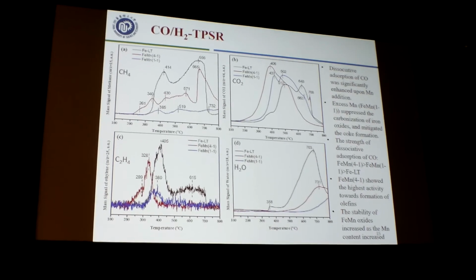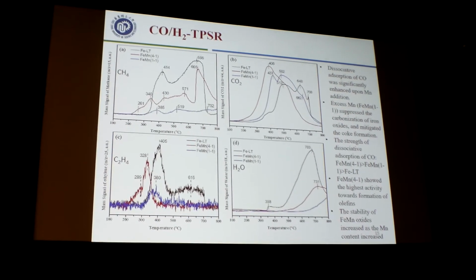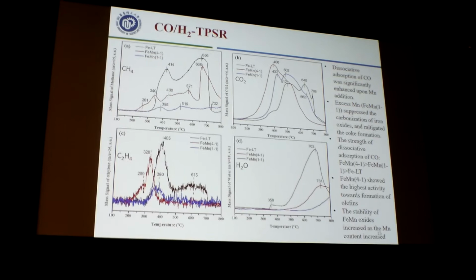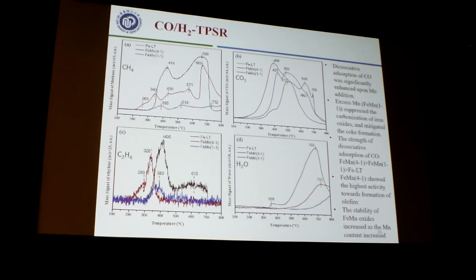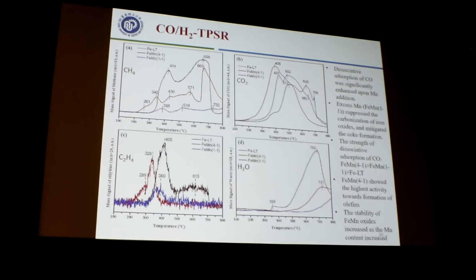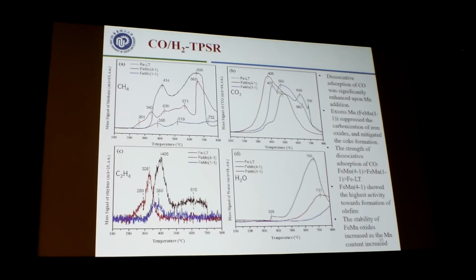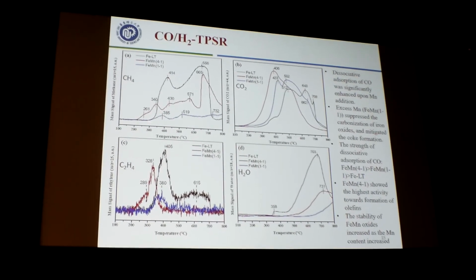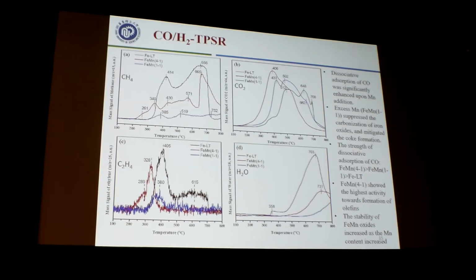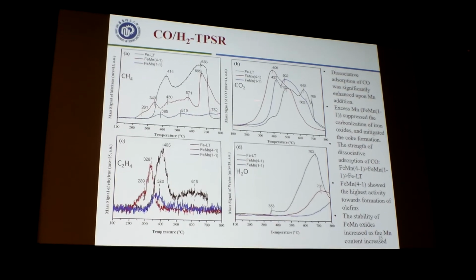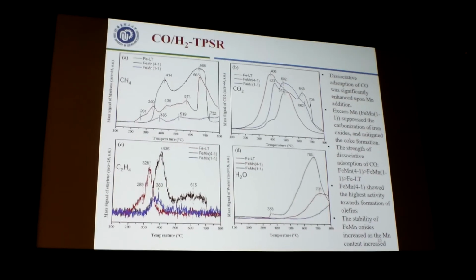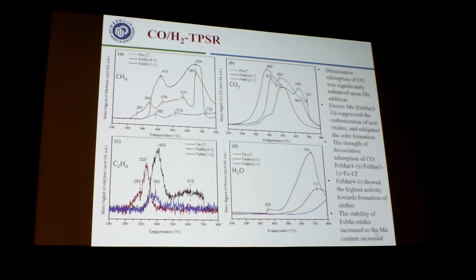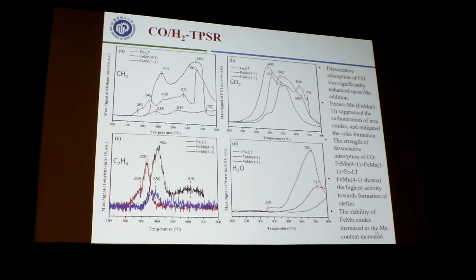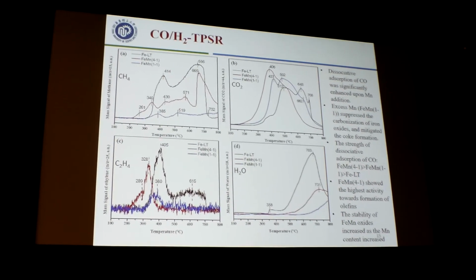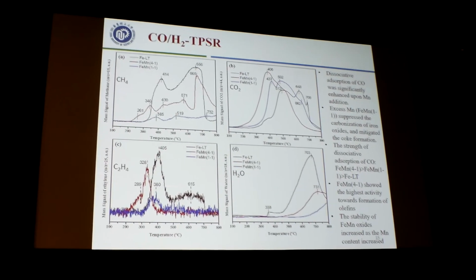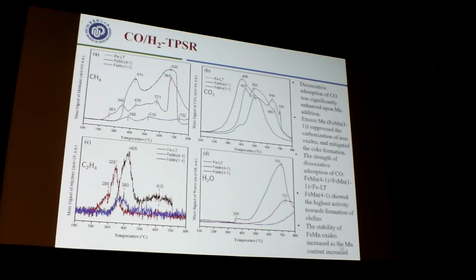So, to elucidate the effect of the manganese during the reaction, we conducted the CO and the H2 TPSR experiment. So here we can see as we increase the loading amount of the manganese, the dissociative adsorption of the CO was significantly enhanced. You can see also the selectivity of the olefins are enhanced as well.